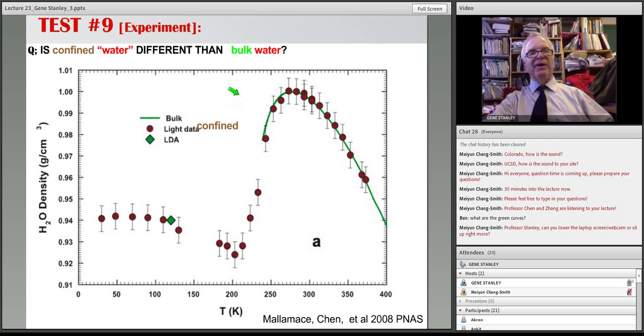But that does not mean that all its properties are totally different. Only the freezing property is different. For example, this green curve is a fit to data, real data, on bulk water. You see the legend says bulk. And as you see, going into the supercooled region, the ordinary density has its maximum at 4 Celsius and then continues to decrease. We even argue that it can be fit with an apparent divergence as it decreases to minus infinity. And so that's the behavior of bulk water.